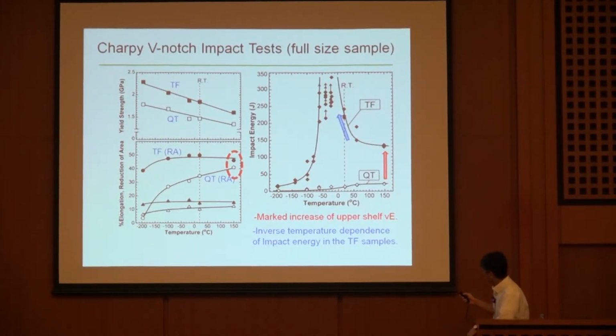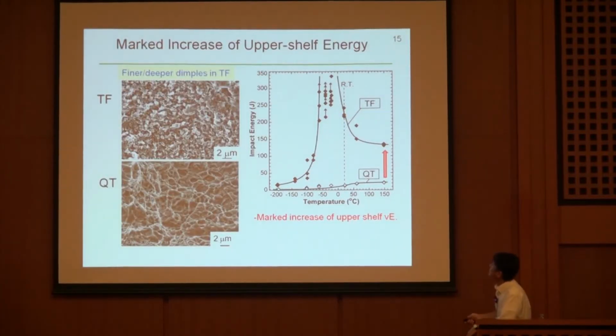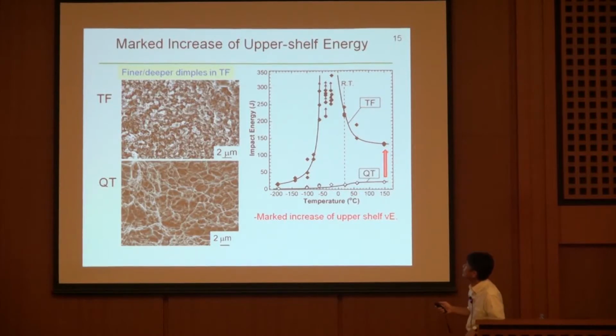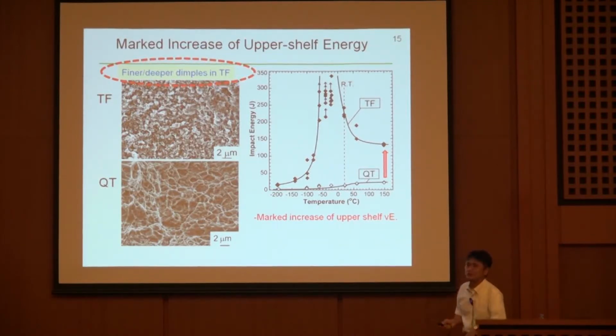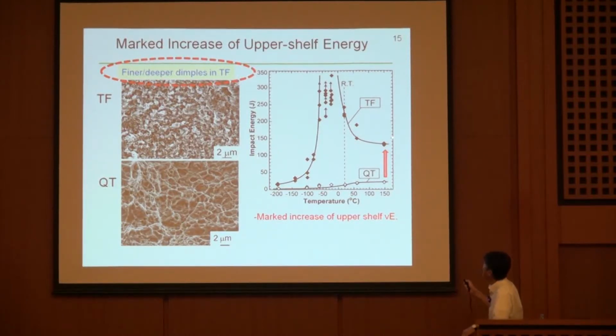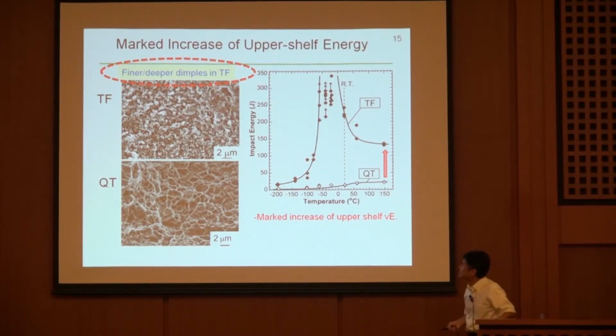But firstly, we discussed this jump. When you look at ductility, the changes are just here, so it isn't enough to explain this large jump in impact energy by ductility. So then we looked at fractography. Finer, deeper dimples in the new microstructure were obtained. This could be one of the reasons for this jump, but we are still studying another or additional reason to explain it.